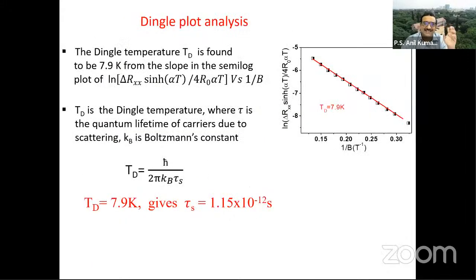Another interesting analysis that we can do is something called a Dingle plot analysis. So if you take this particular form, you convert your resistance into it and then plot it against the inverse of the field, then from this plot, you can get something called a Dingle temperature. The Dingle temperature is a temperature that Dingle used to reconcile between the theoretical predictions of Landau and these de Haas-Shubnikov oscillations. So this Dingle temperature also gives you a lot of information about the system, about the lifetime, etc.